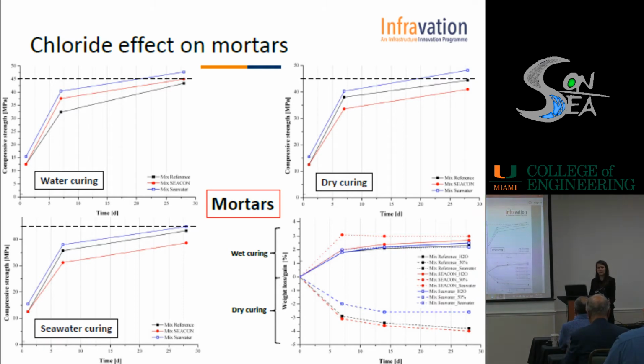Then we cured the samples after 24 hours from molding in three different conditions: water curing at 20 degrees, dry curing at 50% relative humidity and 20 degrees, and in seawater. And then we performed the compressive strength test, and then we determined the weight of the samples to understand if there is a loss or a gain in weight due to the curing conditions.